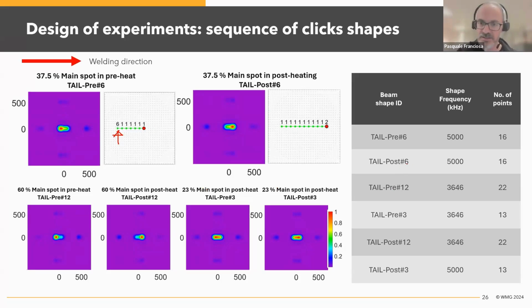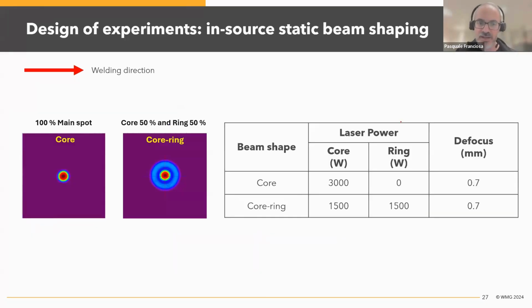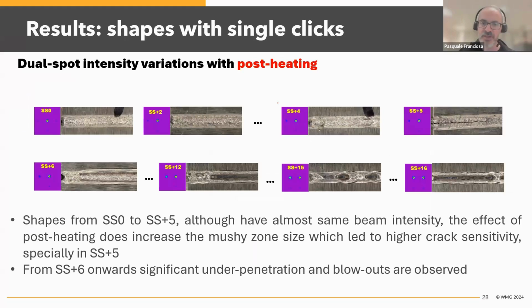Again, the welding speed was exactly the same, 110 millimeters a second. And the power was adjusted to get full penetration across all those welds. Those are the parameters for the core ring. Again, the power has been adjusted in such a way that we got full penetration on the weld. Full penetration was the basic requirement to say the welds are comparable in terms of weld profile.